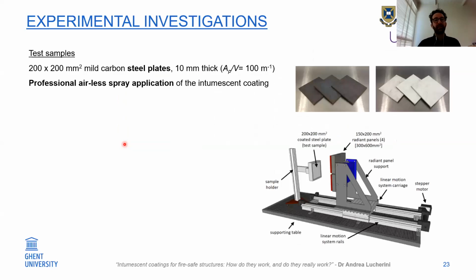Regarding the experimental investigation and what I tested during my PhD, based on the size of the radiant panel, I used mild carbon steel plates, 200 by 200 square millimeters, 10 millimeters thick, with a section factor of 100 meter to the power -1. You can see the test samples here. The samples were professionally coated with an airless spray application using the intumescent coating I mentioned earlier.